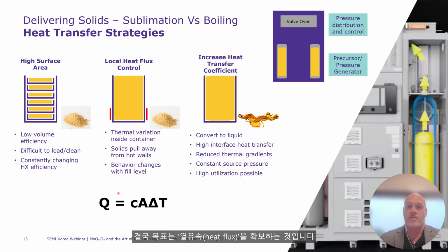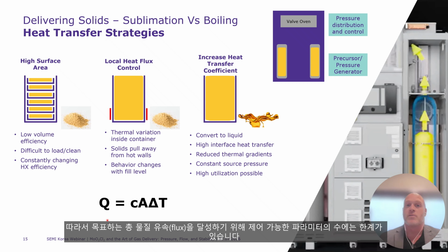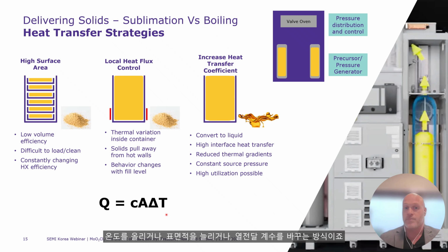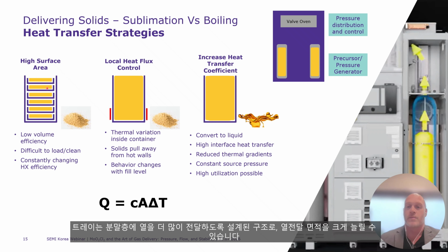Fundamentally, what you're trying to get to is a heat flux. There are only so many parameters to tweak to get to your overall material flux. You can tweak temperature, you can tweak surface area, or you can tweak your heat transfer coefficient. Here are very basic cartoons of different strategies to do that. For example, if you want to increase your area, so high surface area, you can do something like a tray system, where that tray system is fundamentally intended to drive heat into the powder bed. In this scenario, you're driving your heat transfer area up.